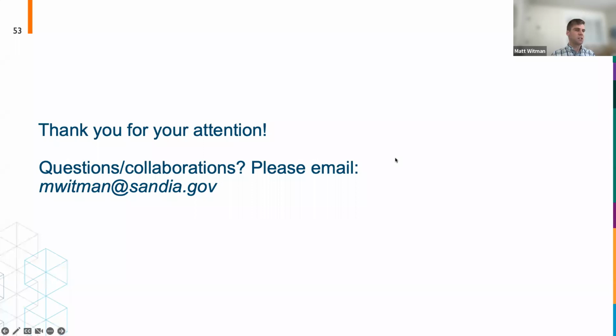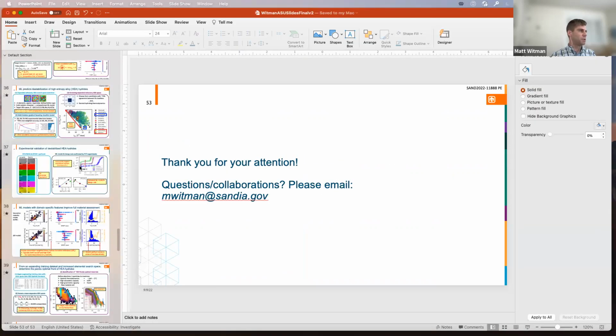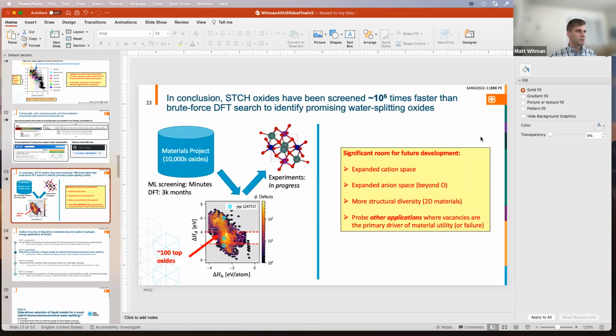But in terms of what goes into the machine learning model, because you're just inputting a crystal structure, if we had DFT calculations that did represent surface structures, there would be no change to the machine learning approach to actually do those predictions. You would just feed in your slab model or whatever it is. That's a good point. If I go back to this slide in terms of opportunities for next steps, we want to start getting more structural diversity, and that could be 2D materials, but that could also, of course, be slab materials or defects where the local environment is not bulk but is terminated at some point. So yeah, thanks for the question.